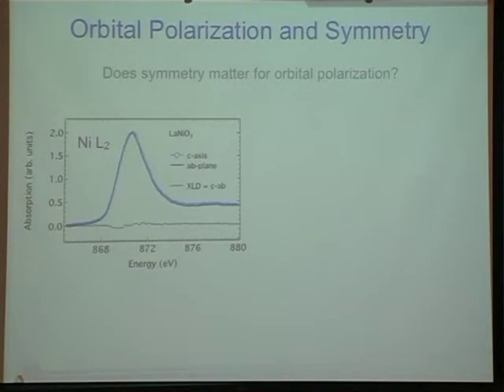And the first thing is we want to measure the polarization of the orbitals. So how do we do that? Actually, I forgot to put the picture in before this. The idea is we have a film with the c-axis oriented out of plane. So what I can do is put the polarization of the X-ray either out of plane or in plane, and I can probe the differences between those 2 electronic orbitals. And what you find in lanthanum nickelate, even though this is under 2% tensile strain, we see no orbital polarization whatsoever.